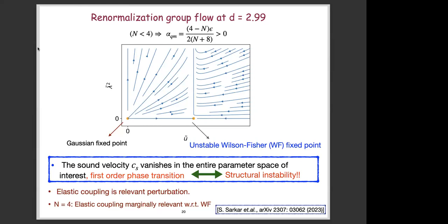We also have a Wilson-Fisher fixed point, which is given by this dot here, on this axis, and this is stable only along this u-axis, but once you turn on a little bit of elastic coupling, it's actually unstable and the flow is towards strong coupling. So this runaway flow suggests a first order transition in the system. And it can be shown that when this lambda tilde is diverging, the sound velocity vanishes in this entire parameter space.